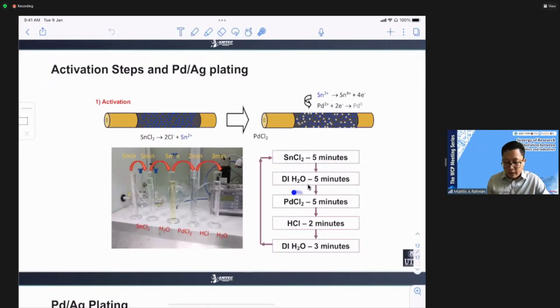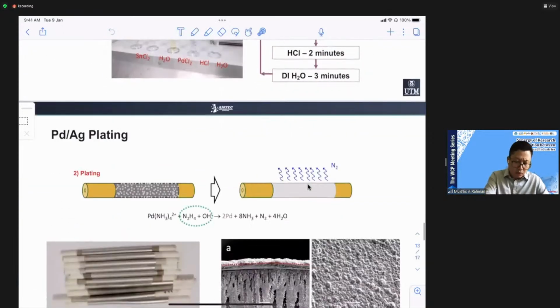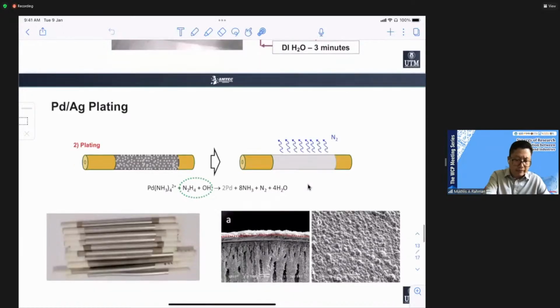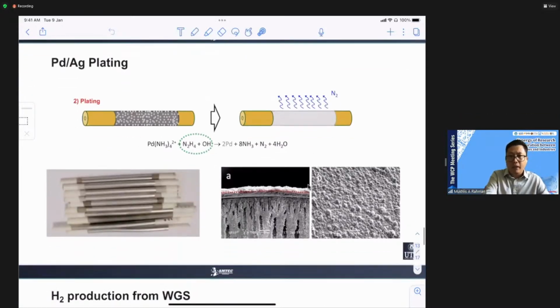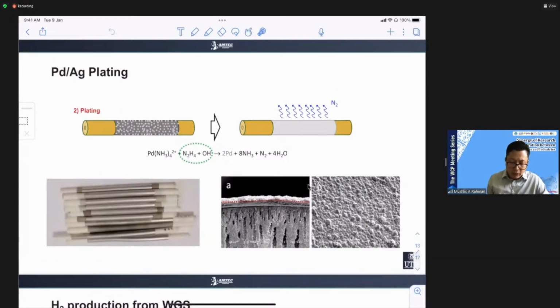So using stannum chloride and palladium chloride, this is the route of embedding the palladium on top of our support. This process is repeated up to 7 times so that we get a very good layer of palladium seed. After this process, we coat that seed with palladium. In fact, 2 layers of palladium need to be done. You need to do palladium coating twice using the electroless plating technique. Hydrazine is used, and EDTA is used as an additive for this process.